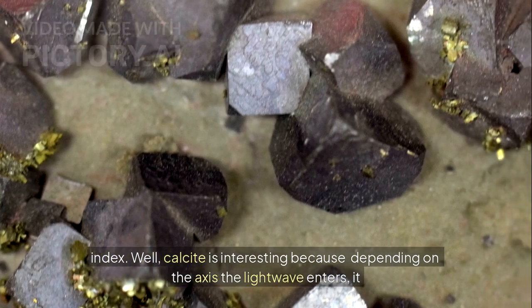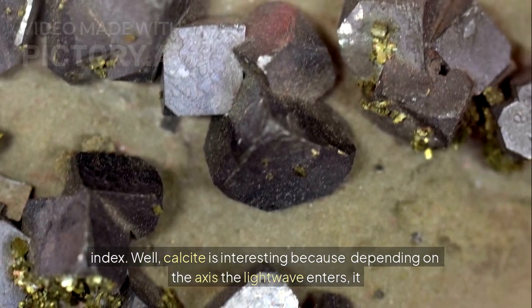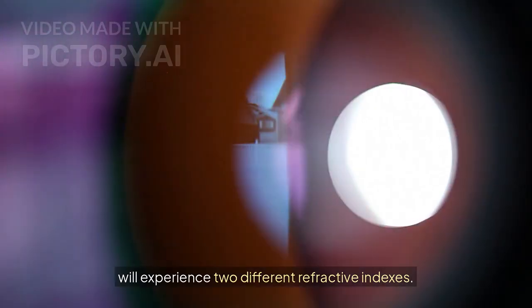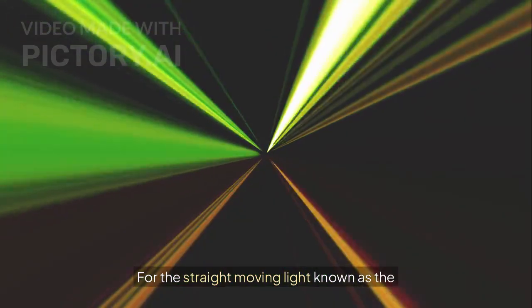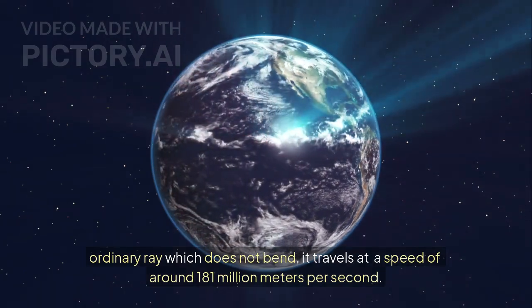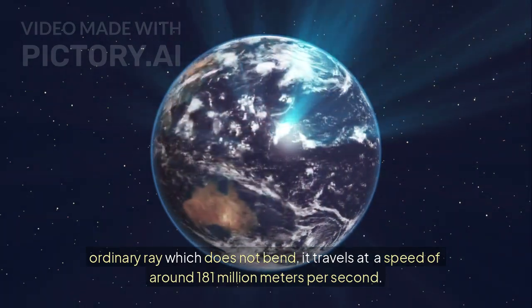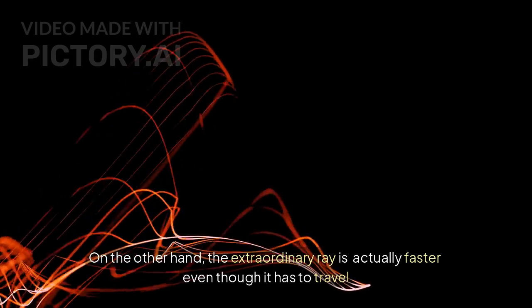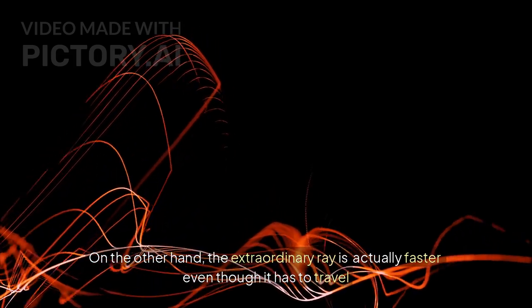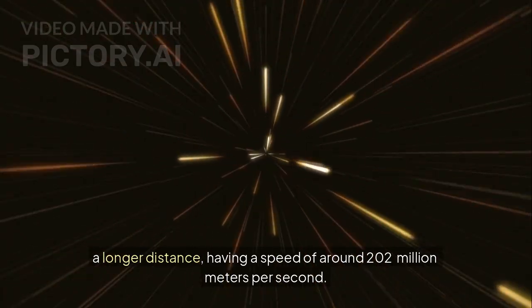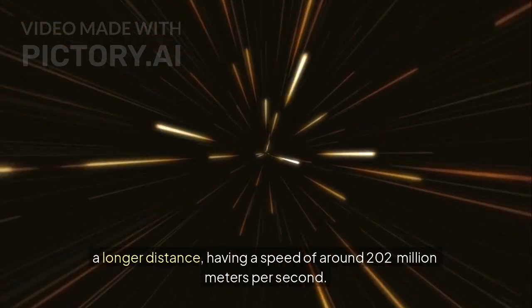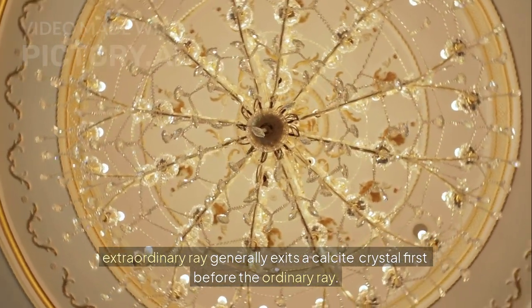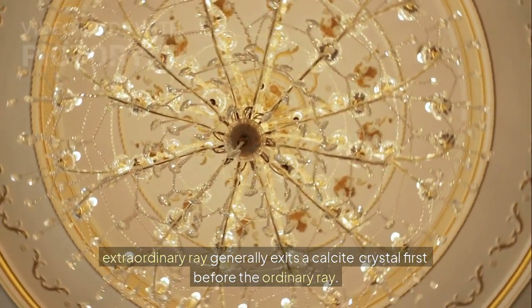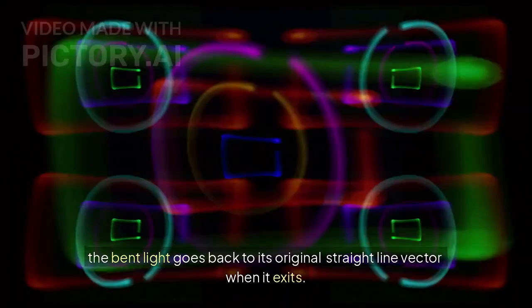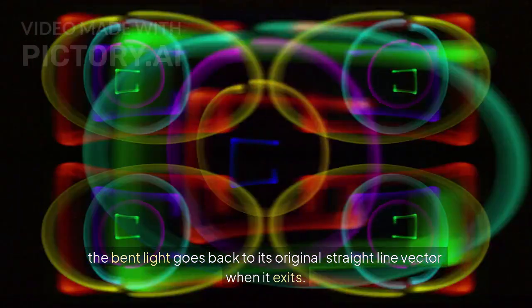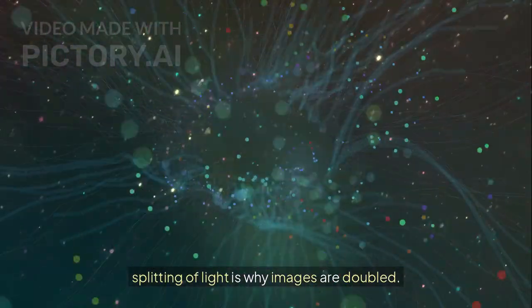Well, calcite is interesting because depending on the axis the light wave enters, it will experience two different refractive indexes. For the straight-moving light known as the ordinary ray, which does not bend, it travels at a speed of around 181 million meters per second. On the other hand, the extraordinary ray is actually faster even though it has to travel a longer distance, having a speed of around 202 million meters per second. This means that the extraordinary ray generally exits a calcite crystal first before the ordinary ray. And the bent light goes back to its original straight-line vector when it exits. This splitting of light is why images are doubled.